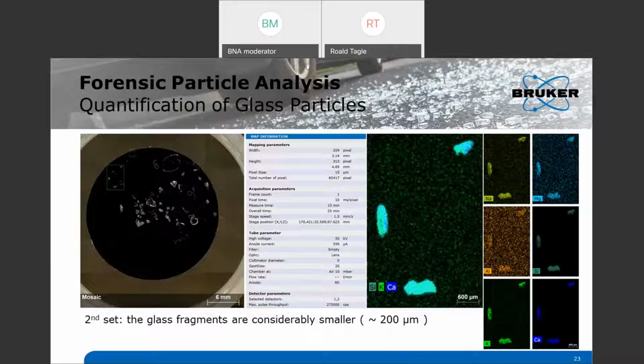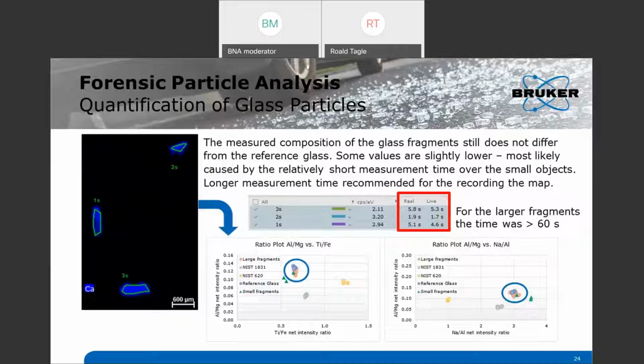The acquisition time per pixel was 10 milliseconds, and it was a total number of 65,470 single points in this elemental distribution. Basically, from here on, similar to what we did before with the larger objects, we can cut objects out of my sample, and these will be added together by the software into one pixel. As you see here, some of these objects are already labeled 1, 2, and 3. On the right side, you see the measurement time behind each of these objects. And as you can see, especially object number 2, with approximately 2 seconds of real time and 1.7 seconds acquisition time, has a relatively short measurement time.